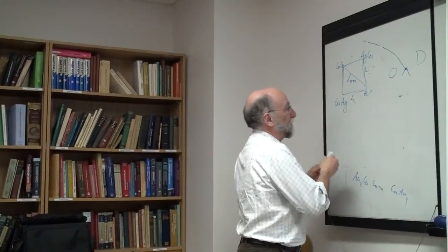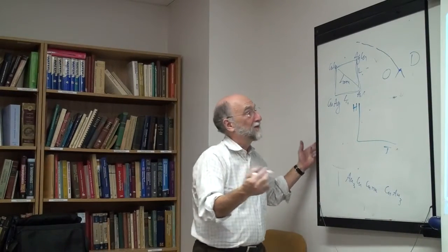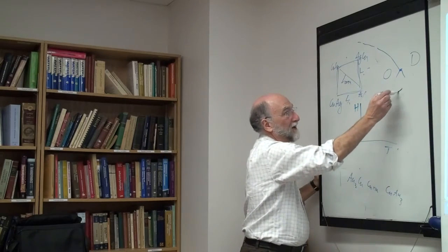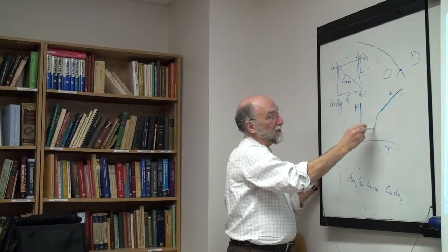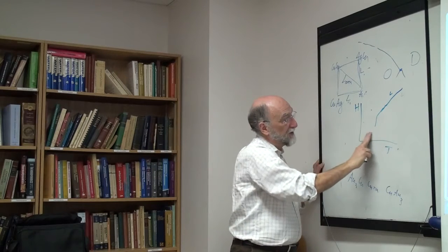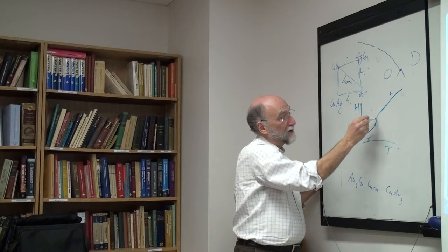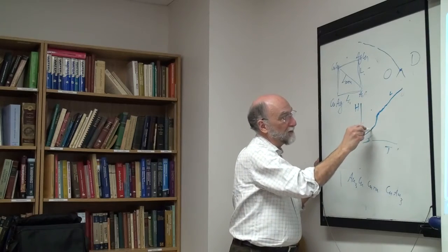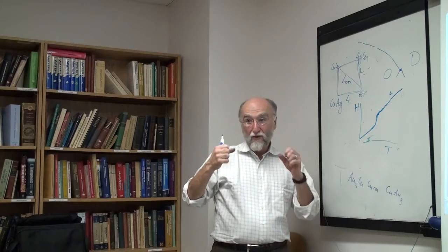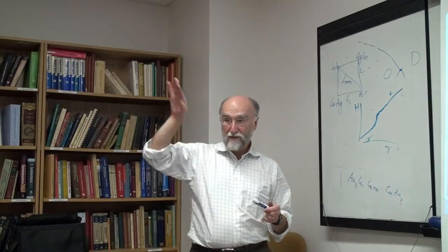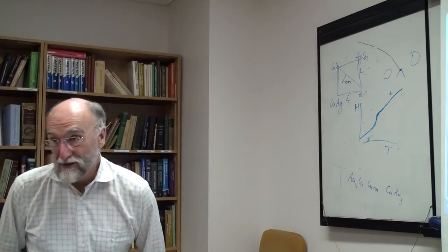But if you cool silica down and plot the heat content versus temperature for SiO2, and you prevent crystallization, which is hard to do, you have a liquid. You pass the melting point, but nothing freezes. It comes down, just getting more and more viscous, but then there is a region in which it does tend to go down like this, and then it tends to level off again. What's happening is that up here the way things can vibrate suddenly becomes locked in, and over a fairly narrow temperature range the viscosity shoots up even more, and you end up with something that's more rigid. But there's not an abrupt change in slope. You can approximate it as a second-order transition if you want, but it isn't.